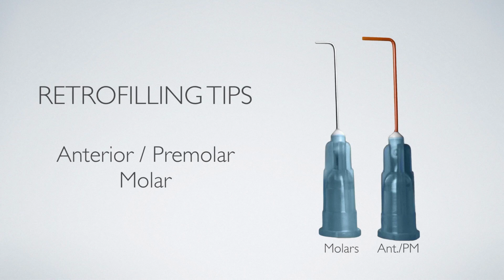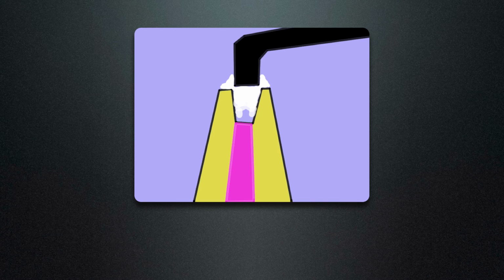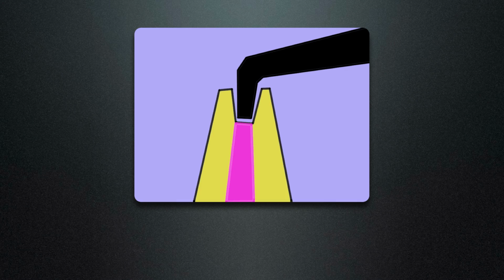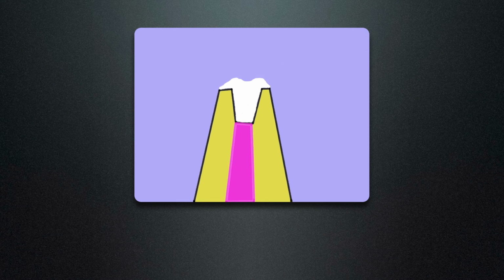So we've developed these specialized tips for delivering the syringeable material all the way down to the end. The key thing to remember is that you can't inject the sealer material right from the cavosurface orifice, because otherwise you're going to trap voids in there. The same way with backfilling with your Obtura gun, or placing your core material, you've got to take the nozzle of that syringeable material all the way down to the base of the preparation and then back up so that you don't actually trap any voids.